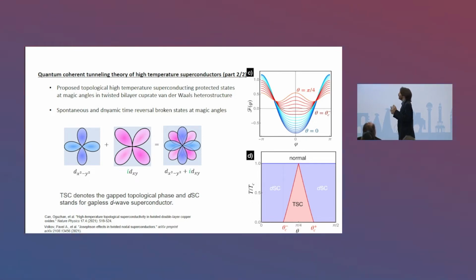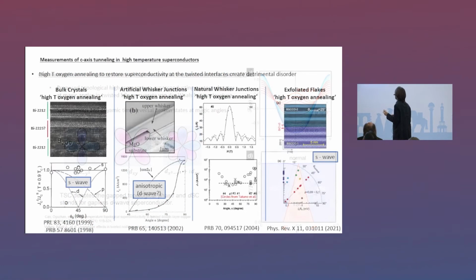And not only that, you can also realize spontaneously time-broken states or dynamic time-broken states, depending on which angle you are at. This means, for example, that if you have a nodal gap and you apply a current across your Josephson junction, then you basically deplete the nodal gap and open a gap. So then the system completely changes. And these dynamic states and spontaneously broken states are also what I'm going to discuss.